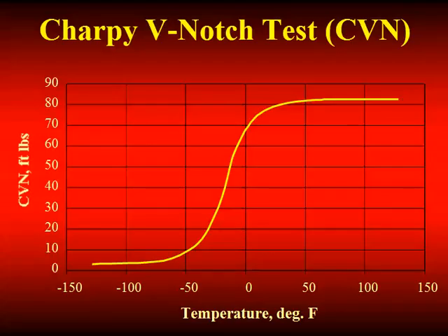If you measure that energy at high temperatures, you get relatively high values of toughness. If you measure the same material at low temperatures, you get low values. Between the high values and the low values, we go through something called the transition. The transition is made over a temperature range, and we typically call that transition temperature. Transition temperatures, like cholesterol, low values are good. So the lower the transition temperature, the tougher the steel is at low temperatures.